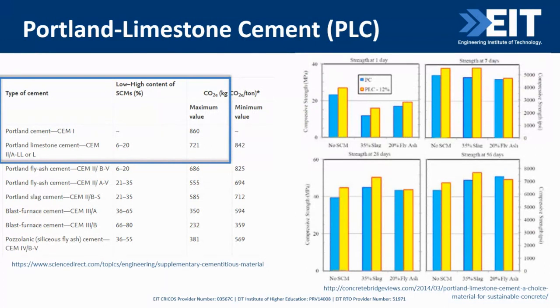For many applications, Portland limestone cement can actually provide equivalent or sometimes even better performance with reduced environmental impacts. For example, this figure on the right shows the strength for concrete made with a water to cementitious ratio of about 0.4, for specimens without any supplementary cementitious materials, and with about 35% of slag, or with 20% of fly ash at different ages.